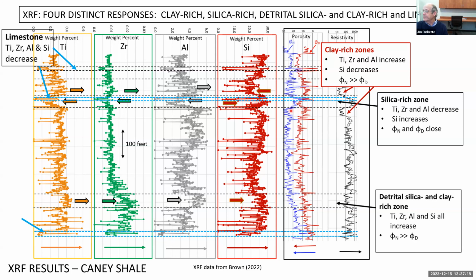And in this case, from the limited number of logs that we've seen calibrated back to core, when those two separate, that's indicating high neutron porosity, high clay content, and those are more ductile, non-reservoir zones. While when those two curves approach each other, it's indicating we have less clay content, decreasing neutron porosity, and high resistivity, and that is a productive zone.